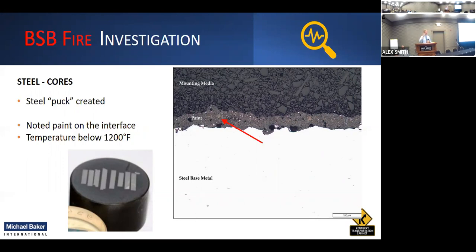There's a black medium of plastic that goes in there. They polish this thing down. The polishing process was pretty fascinating. Actually, when they grind and polish this thing down to the microns, they have a polishing cloth, but the liquid that they drop in there has different diameter diamond bits.